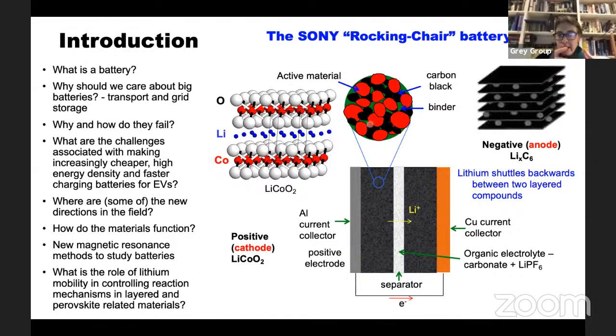And then when you make the whole electrode, you've got to combine it all together, essentially with carbon black to get the electrons in, and a binder such as a polymer to hold the whole thing together as you expand and contract the materials as the lithiums are coming out. And then you've got to have porosity so that the lithium ions can get in via this organic electrolyte. And all of this has got to last for the many times that you want to cycle your battery, whether it's in your phone or an electric vehicle where it might want to last for 7 to 10 years, or on the grid where this might be 20 years. And so this is a real chemical, physical, material science and engineering challenge to get this to work.